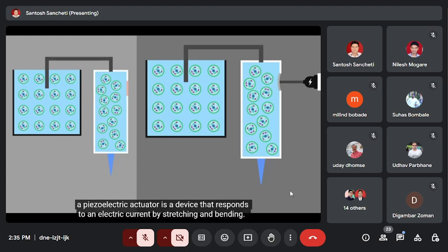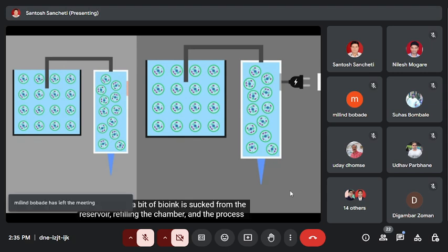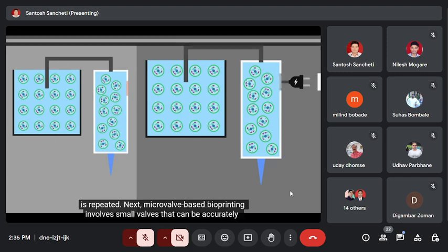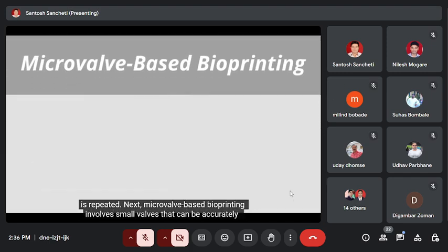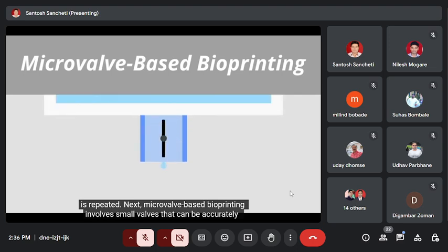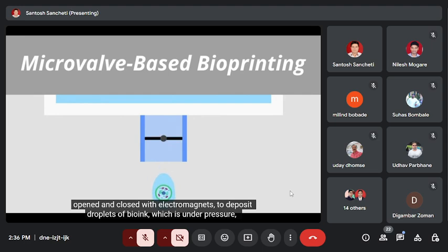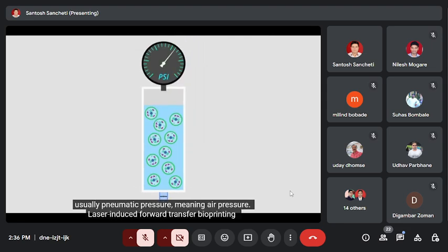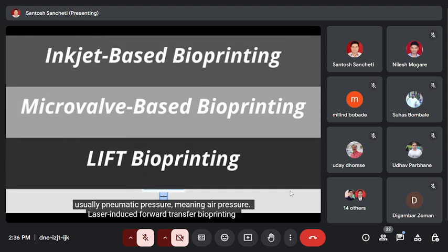By the way, a piezoelectric actuator is a device that responds to an electric current by stretching and bending. Then, when the electric current to the piezoelectric actuator ceases, the shape returns to normal, and a bit of bioink is sucked from the reservoir, refilling the chamber, and the process is repeated. Next, microvalve-based bioprinting involves small valves that can be accurately opened and closed with electromagnets to deposit droplets of bioink, which is under pressure, usually pneumatic pressure, meaning air pressure.